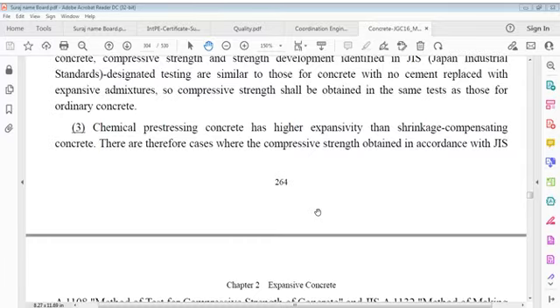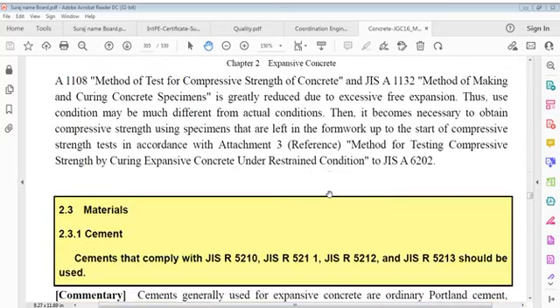There are therefore cases where compressive strength obtained in accordance with the method of test for compressive strength of concrete, method of making and curing concrete specimen, is greatly reduced due to excessive free expansion. Thus, the test condition may be much different from actual conditions. It becomes necessary to obtain compressive strength using specimens that are left in formwork up to the start of compressive strength tests in accordance with the method of testing compressive strength.